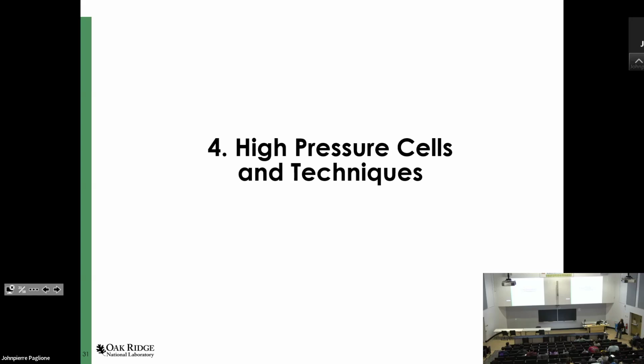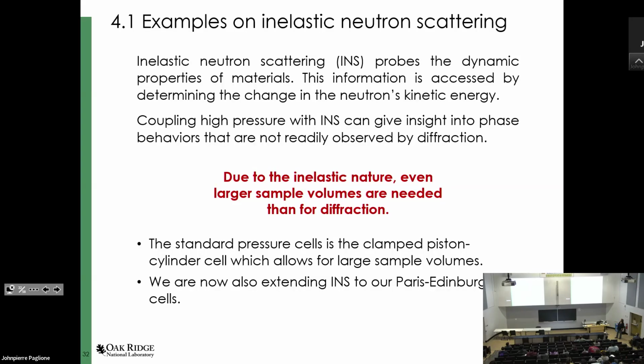Okay, so now let's talk a little bit about high pressure cells. I want to actually start with inelastic neutron scattering to work my way up to the highest pressures. Inelastic scattering has a lot of advantages in the information you can access. You can probe information you cannot probe with diffraction, of course. But because it's an inelastic process, you need an even larger sample volume. The usual guideline is that you need a sample volume 100 times as big. So again, for high pressure neutron scattering, this is not an ideal scenario. That's the reason why the standard cell for inelastic neutron scattering is still largely the clamped cell.